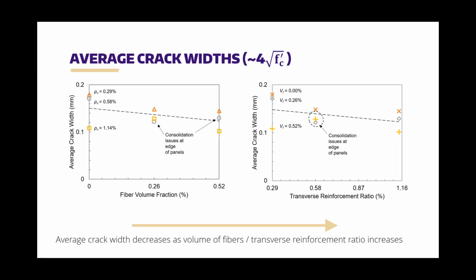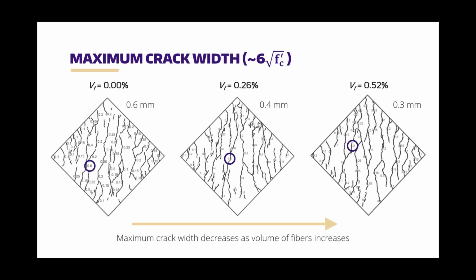Those are those panels that had consolidation issues. But overall, the general trend is true. So you see that makes sense. That's what we expect. Same thing's true of the maximum crack width. So this is again at a stress level about 6 root f'c.